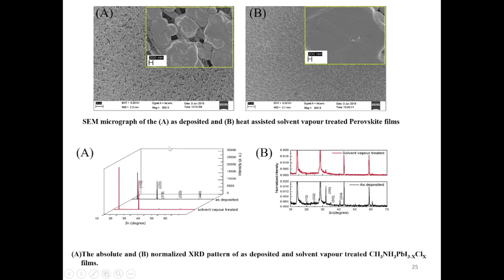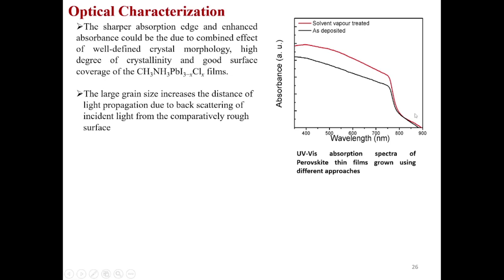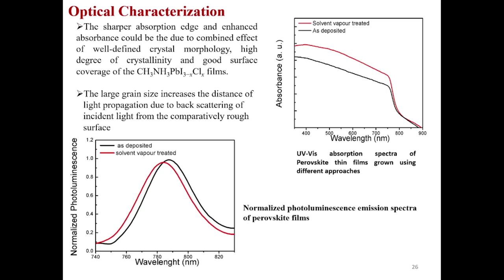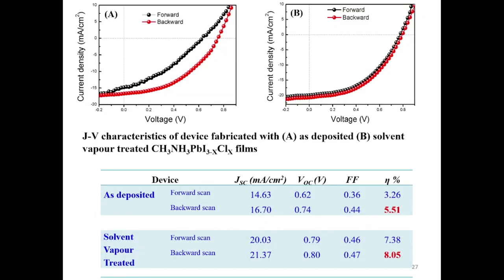If you see the optical absorption, solvent vapor treated films show comparatively better or more absorption, and the grain size increases. This increases light scattering of incident light. This work shows improved efficiency as given here. Although efficiency is not that much high because these devices are not fabricated in all ideal conditions, but we have compared in the same atmospheric fabrication conditions. This vapor treatment increases VOC, JSC, and even fill factor.